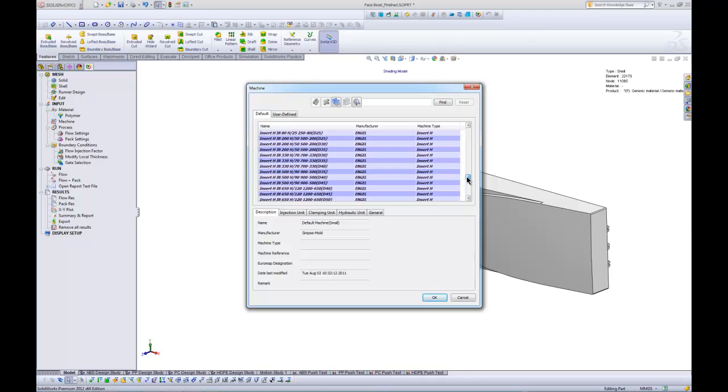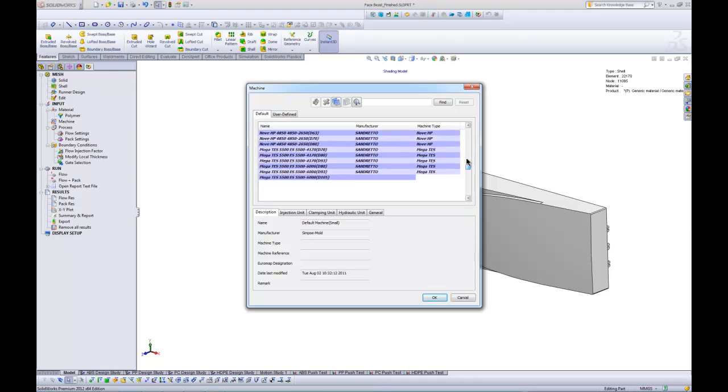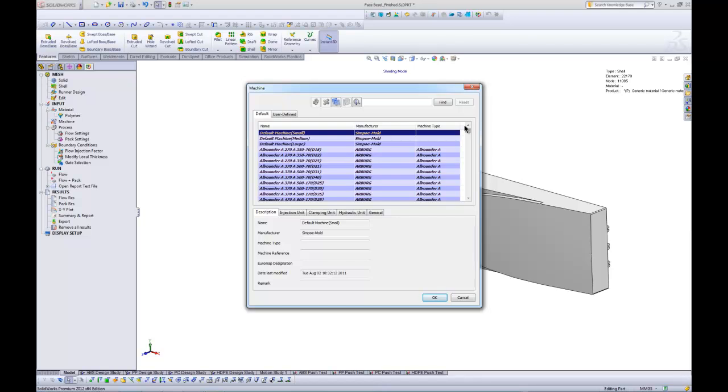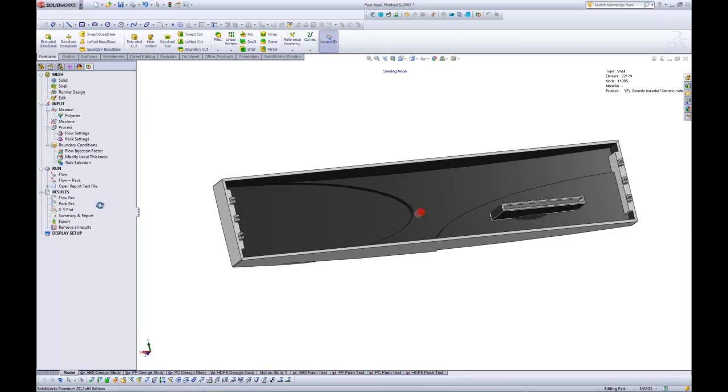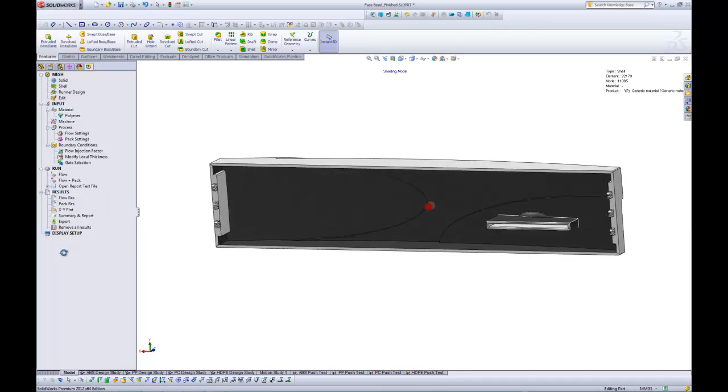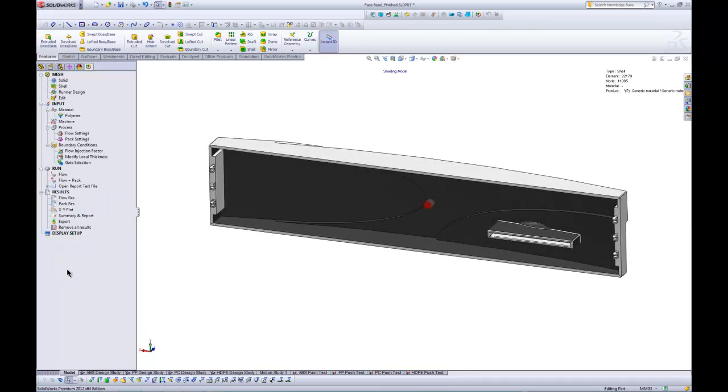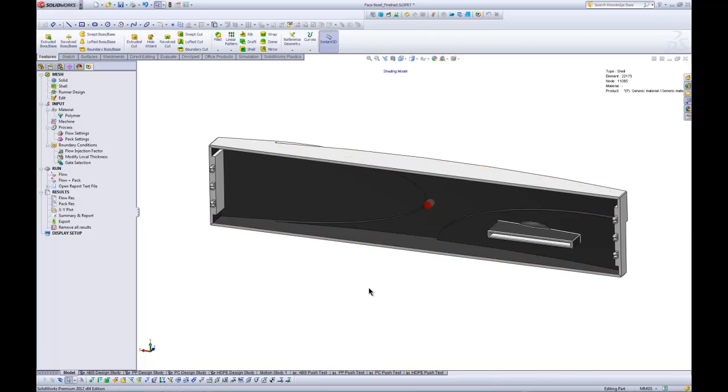But again, if your machine isn't, you can always create your own user defined. The machine's important because it specifies the injection pressure. And that's one of the things that we really want to monitor. We want to have a low enough injection pressure, probably around 15,000 PSI's, to cut off before you need to go from small machines to large machines. It also tells us things like the clamping force and how much material it can push through. We can also specify flow settings, pack settings. One of the nice things, we can say exactly where we want our gate to be located. So you can see in this case, we're saying that we want the gate to be back here. We can specify the properties of the gate, so its diameter.